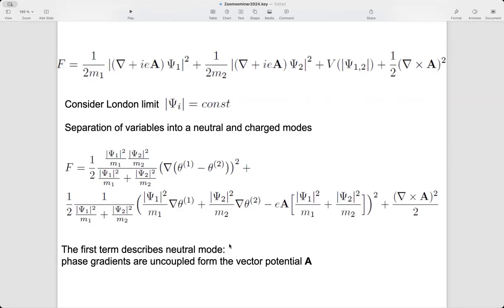Here, if one would start winding phase one, the winding in the phase cannot be asymptotically compensated by the vector potential. There is no vector potential here. So this thing in the brackets will go as 1 over r, 1 over the distance from the center of the vortex core, and it will have a logarithmically divergent contribution if one puts in a vortex in the phase one.